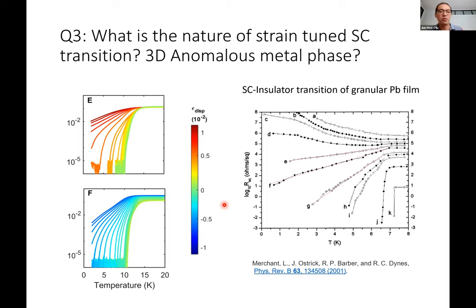The microscopic mechanism could be very different from one system to the other. For example, it could be coming from local ferroquadrupolar orders, or it could be coming from the spin fluctuations, for example, like in the iron-based superconductor, fluctuating density wave. But I think the spirit is that there is a true instability in the electronic part of the free energy. Because in this case, even if we fix a strain, so just say clamp a sample, there is no way to stop the structural fluctuation, right? So it's still somehow coupled with the electronic anisotropy.